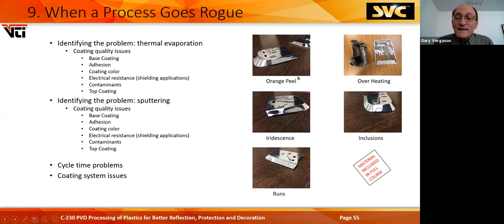Everything from, this is orange peel on the side of this. The base coat was rough. Iridescence, this is possibly caused with uncured base coat. You got outgassing coming when the aluminum is arriving on that surface. Doesn't show up very well, but runs aren't acceptable. When you're setting a process up, sometimes you overheat some parts and they melt. Right, Josh? And you can have inclusions, a speck of dirt that gets in the part. Some customers will let you have an inclusion for so many inches, but the larger the part you have, the more difficult it is to get a perfect part.